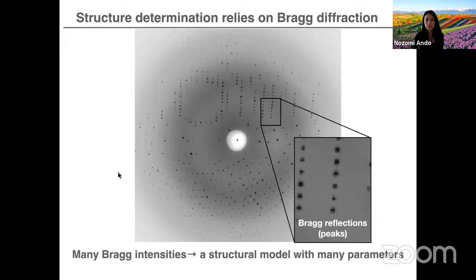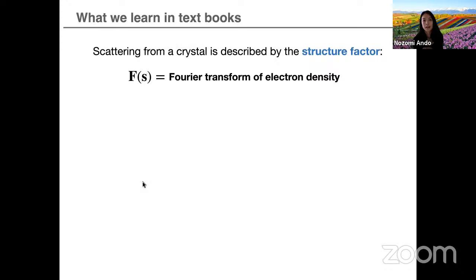Okay, so this is nice and all, but there's actually more to diffraction than that. And to illustrate that, it's informative to think about what we learn about crystallography in textbooks. The important thing is that scattering from a crystal can be described as the Fourier transform of the electron density. So this is called the structure factor. All you have to remember is that in the case of X-rays, every electron is scattering because of the incoming X-rays, and the ultimate diffraction pattern or scattering pattern is an interference pattern of those individual scattering events. And that can be described as the Fourier transform of the electron density. And this is a fundamental reason why we can get structural information from scattering-based techniques, crystallography, also cryo-EM, right? And so you can think of this as the scattered wave or the structure factor.